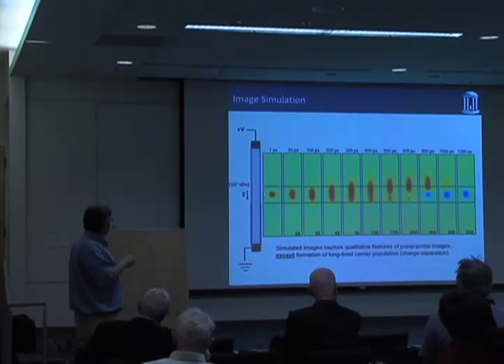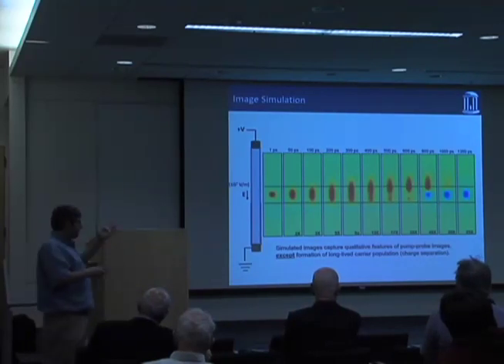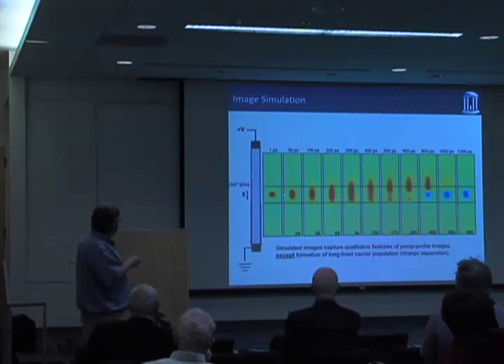So it starts out, and it sort of spreads through diffusion because the carrier density is so high that it could care less about the field. As that happens, some of the carriers sort of spill over into the N-type region. Some of them spill over into the P-type region, but they recombine so quickly in the P-type region that they essentially disappear.